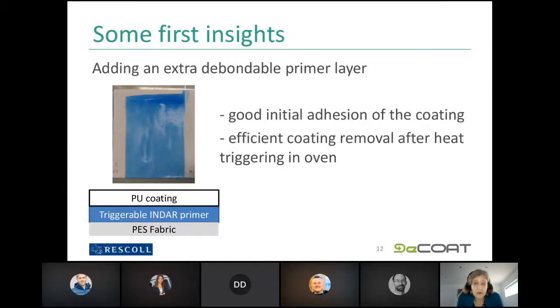A second way that we are looking at is to put, in between the polyester fabric and the polyurethane coating, an additional triggerable primer. This is the one in blue, the Indar primer. On the picture you see the white is the polyester fabric, the blue is the primer, and on top you can see a shiny glossy polyurethane coating.